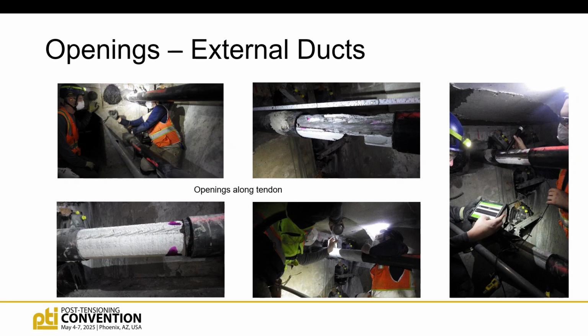So these are a series of photos of a location where we've stripped the sheeting off, right? And we have extracted some grout samples, because you see that missing grout. So we've taken some grout samples. We've also done carbonation testing, and we'll do that typically to look at grout quality. So the purple there is carbonation testing, right? And then on the right here, we're doing corrosion testing, half-cell potential measurements in this case.